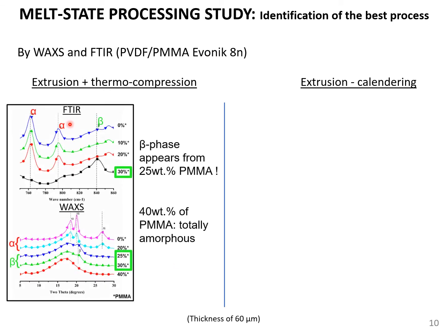First of all, in the case of extrusion thermocompression, the static method, we observe by infrared the appearance of an alpha peak and a beta peak that only appears when you add over 25% PMMA. However, when you add more than 40wt.% PMMA, the film is totally amorphous.